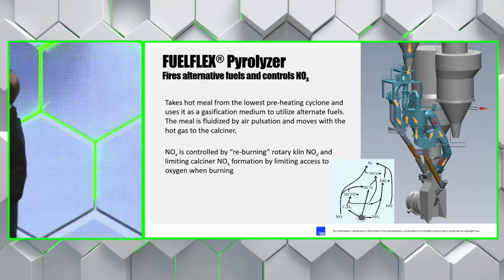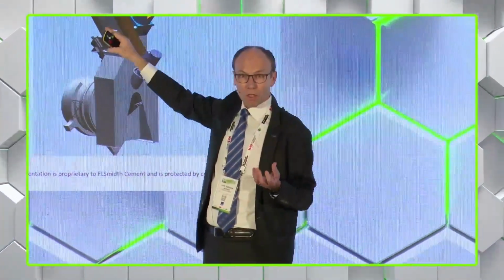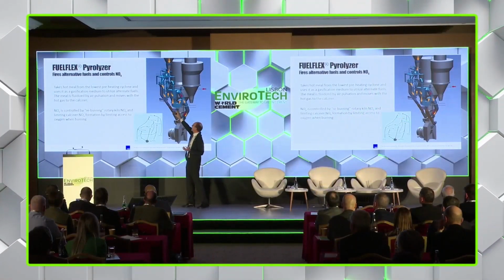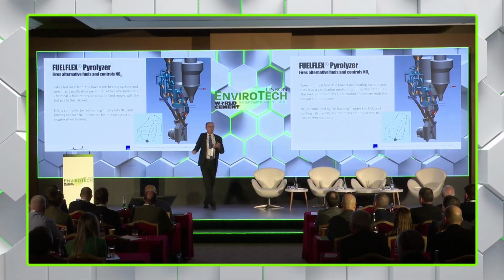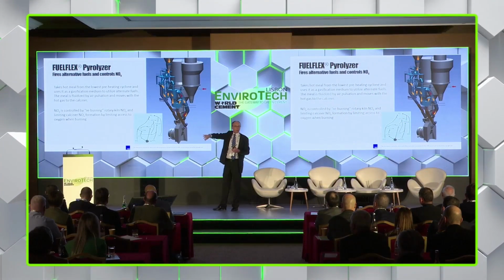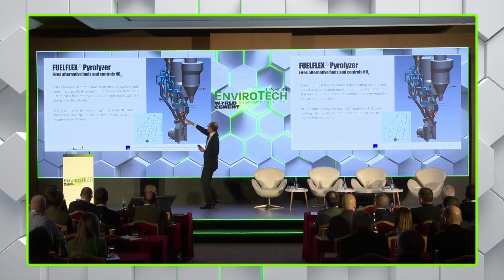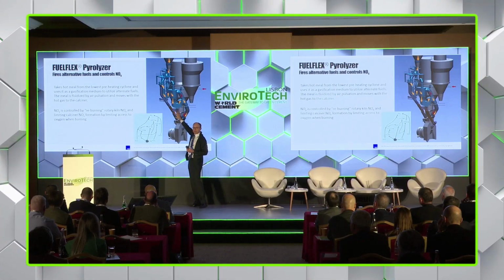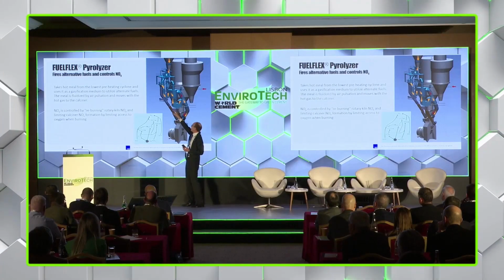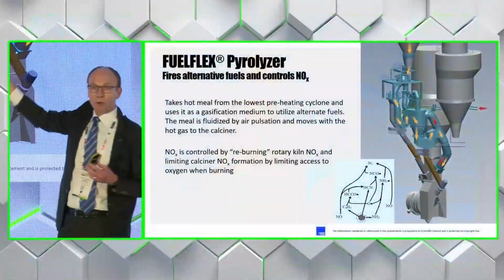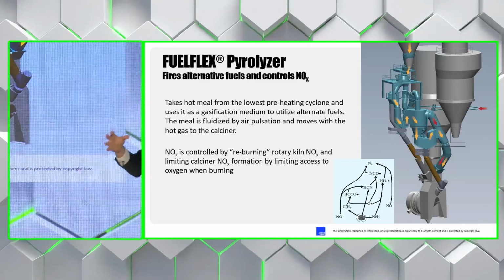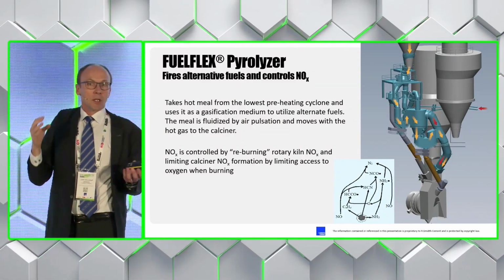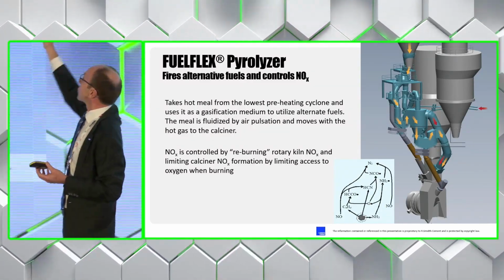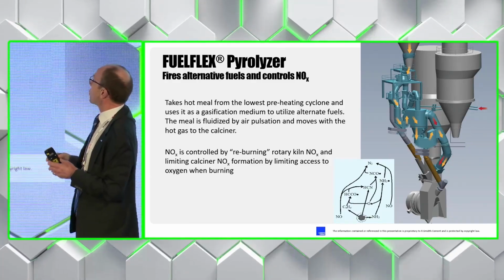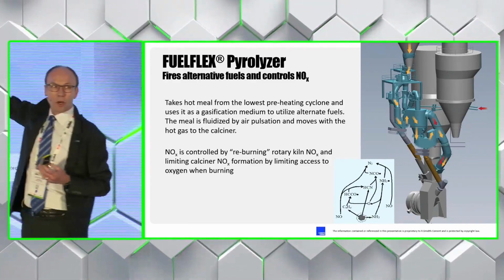What we do here is we use a new pulsed aeration technique to get the meal to flow like water, so it basically behaves like a liquid. As we then pour the hot meal into the inlet leg, it runs out of the outlet leg, continuing over into the main pyrolyzer vessel here. Again, we have pulsed aeration down here where we fluidize the meal, so we have a vessel with fluidized hot meal. To that, we then introduce solid recovered fuel or the alternative fuel. We introduce that into the hot meal.